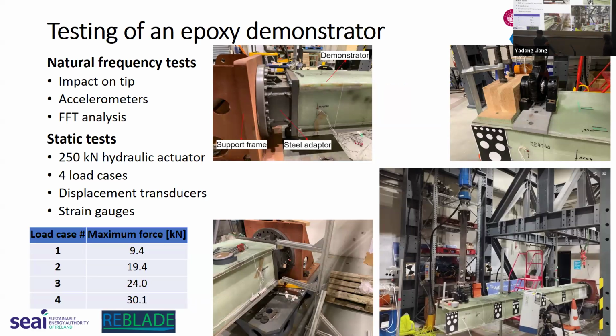Regarding the test, we are going to test the natural frequency and apply a vertical load and study its response under static tests. For the natural frequency test, we use an impact hammer to apply a transient impact on the tip of the demonstrator. It is under free vibration, and we use accelerometers to record this vibration and use fast Fourier transform analysis to get its natural frequency. This natural frequency can be used to indicate the stiffness change of this demonstrator.